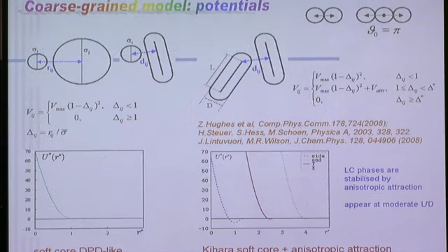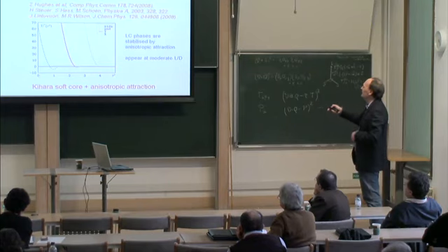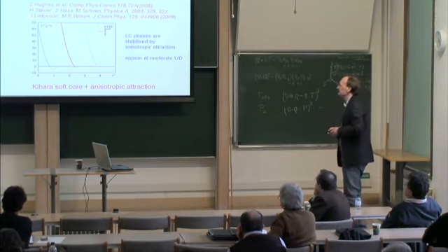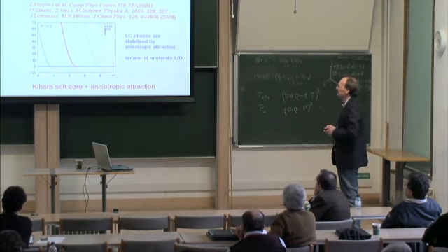The potentials that we use are outlined here. For the spheres and mixed interaction, we just use a very simple quadratic potential, which is typical for dissipative particle dynamics simulations. So it is a soft repulsion here. And for the spherocylinder, we used the potential suggested by Lintuvuori and M.R. Wilson, and it was also in several talks already yesterday and 2 days ago.